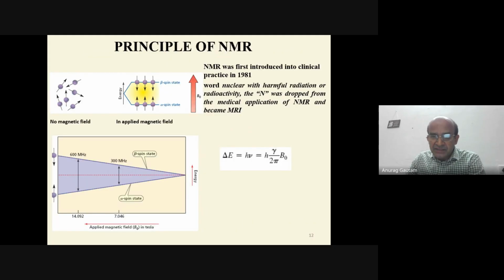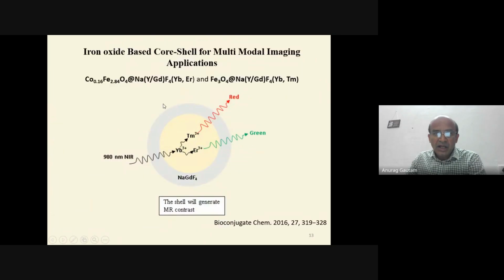Why the more contrast? Because this energy change is directly proportional to the magnetic field, B. So if you go to 7 Tesla, the energy difference here will be very high. The greater the energy difference between the alpha and beta states, the more energy is released when we switch off the pulse, and the higher the contrast. So this is for the iron oxide nanoparticle.